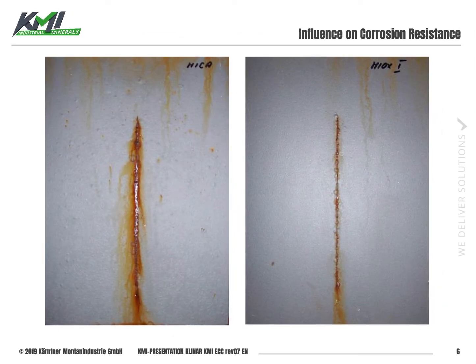The outcome of this you can see on these two test panels. This is previously cleaned steel with a single layer 2K epoxy coating. It's solvent based. On the left hand side we formulated with mica as a filler, and on the right hand side we formulated with Miox at the same pigment volume concentration, and we put the panels in a salt spray test, and you can easily see the difference.